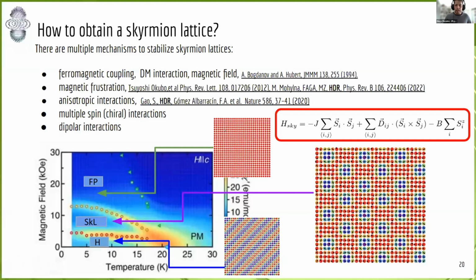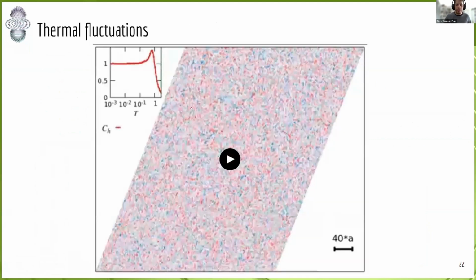We have this pattern where all the magnetic moments are pointing along the field direction, which in this case is perpendicular to your screen. And at intermediate magnetic field, we have the skyrmion lattice with this typical periodic arrangement of skyrmions. Let me show you what happens now when we study the evolution of this skyrmion lattice as a function of temperature. I will show you a very short video.